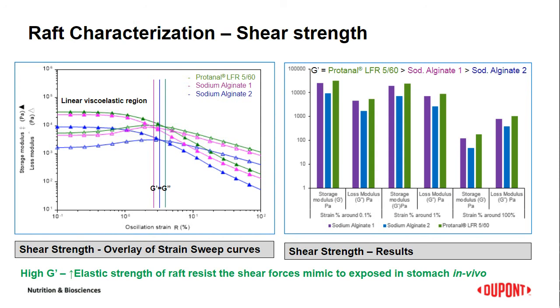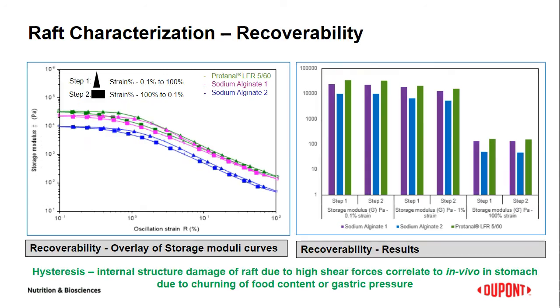The shear strength of the raft is measured in terms of storage and loss modulus. The overlay of the strain sweep curves obtained is shown in the left chart, where the storage modulus of the formulations was higher than that of the loss modulus, and crossover of the modulus was observed around 3% strain. The formulation prepared from Protanal LFR 5/60 has shown higher storage modulus. The higher storage modulus indicates an increase in the elastic strength of the gel, which can resist shear forces correlating to those encountered in the stomach under in-vivo conditions. On the right side, the storage and loss modulus results exhibited by the raft are presented in the bar graph.